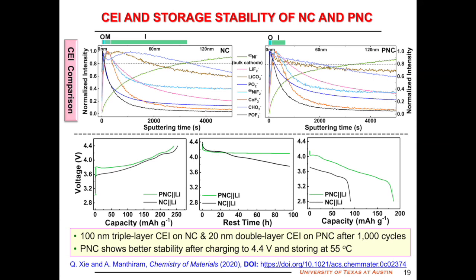We have also charged the two samples to 4.4 volts and stored them at 55 degrees C to see how things change. The sample treated with phosphoric acid has much more stability in the voltage when you store at 55. And also after storing at 55, if you look at the discharge capacity, the phosphoric acid treated sample has higher discharge capacity than the other sample. So surface stabilization is important.